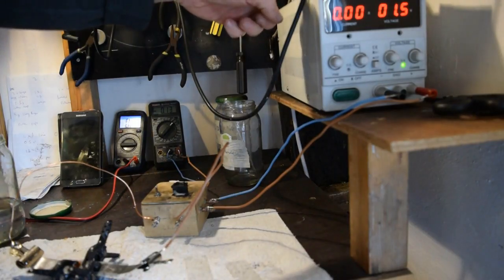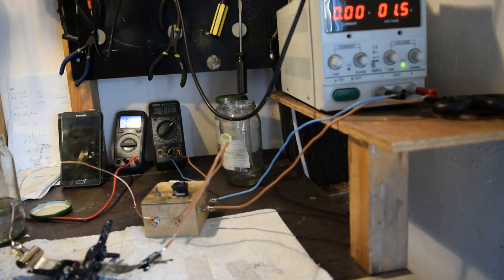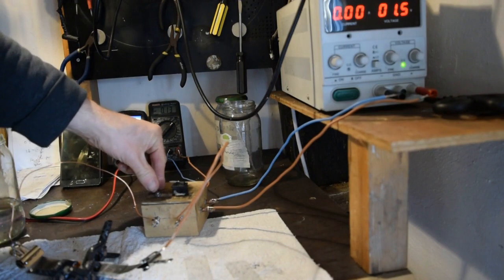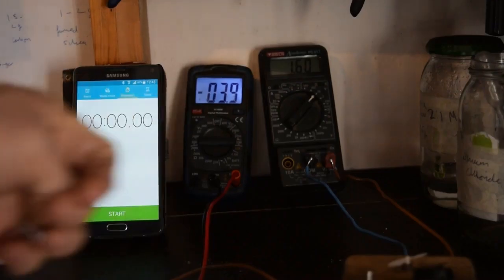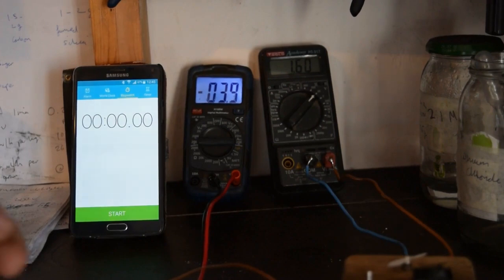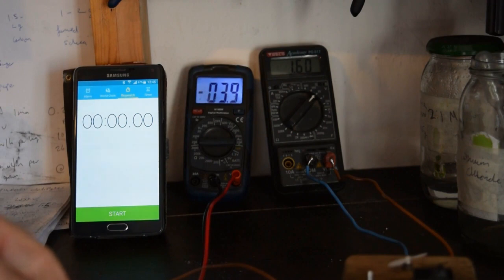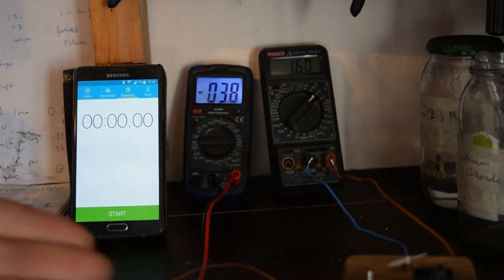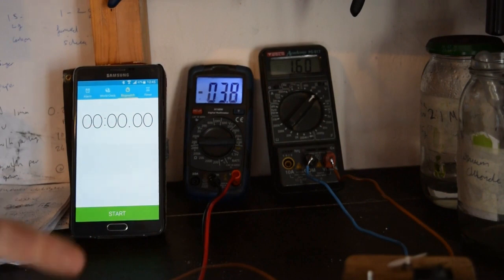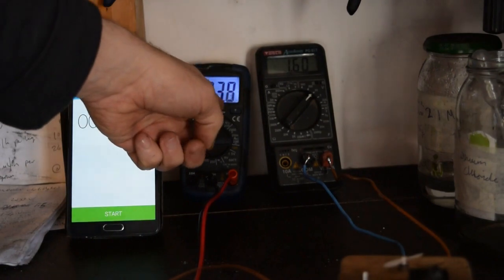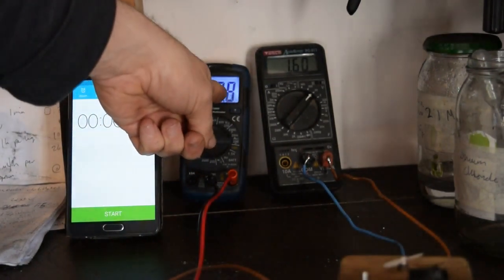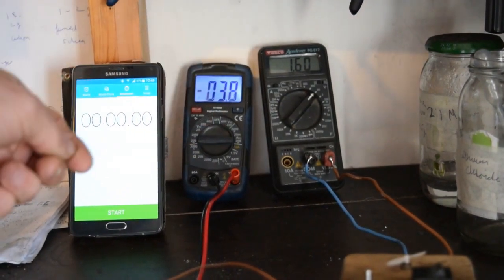So we've got the power supply on here, got it at 1.5, 1.6 volts, and here you'll see the current draw, and so let's give it a charge. Okay, so we've been charging it up for a while, and you've got to bear in mind that this cell is 5 milligrams of active material on about 3 square centimeters, somewhere around there, on the Grafoil, and you can see how flat, or how thin I should say, the layer of carbon that was on the electrode. So we've been charging it for a few minutes, and you can see here the volts, 1.6 volts. And forget about the minus there, it's just down to polarity. It's drawing 3.8 milliamps still at the moment.